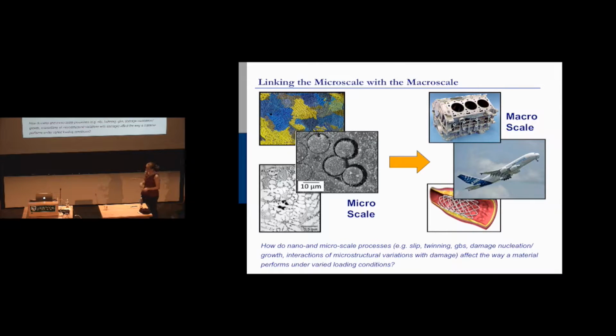So my student was able to look at this microstructure, this grain structure. Titanium is a bit tricky, for those of you who have seen the microstructure, it's got lamella, kind of an alpha beta, and then it has an alpha phase, different phases going on, different structures, almost looks eutectic. And so we were able to look at the microstructure and then watch cracks coming through.